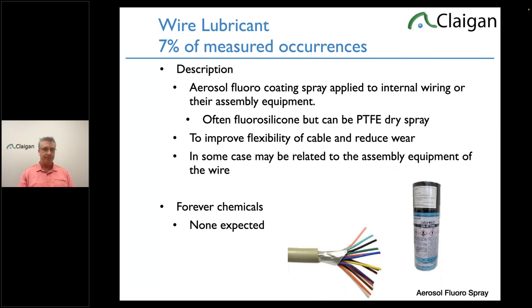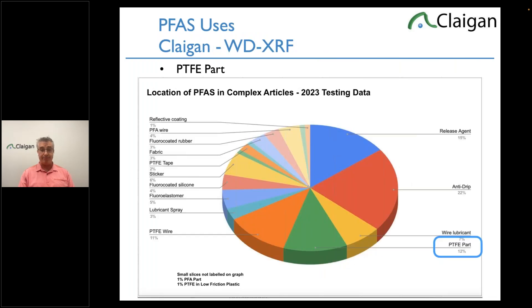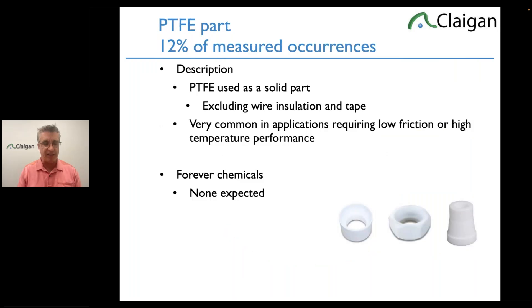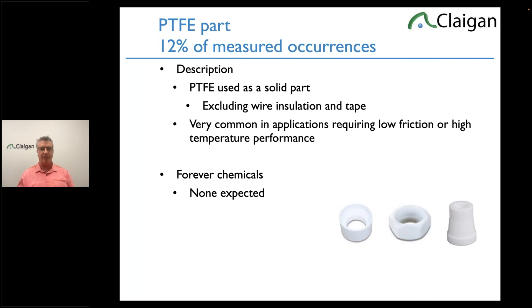About 12% of the time we see an actual PTFE solid part — excluding wire insulation and tape, which are different applications. This is usually a part requiring low friction or high-temperature performance. PTFE is also incredibly acid, base, and oil resistant. Pure PTFE powder — unirradiated — has no PFOA in it and no oxygen bond to degrade into PFOA. We never see any forever chemicals in solid PTFE parts. Very important applications with no chemical risk.